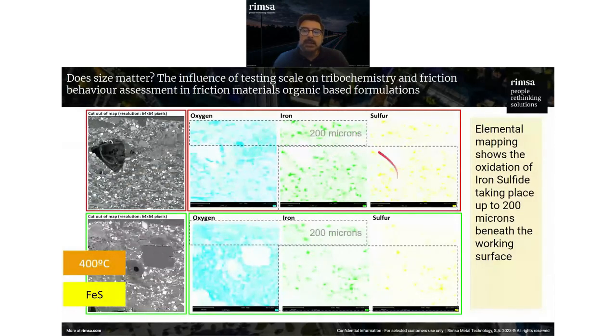We found, the elemental mapping shows that we have the oxidation of iron sulfide taking place up to 200 microns beneath the surface. So we have the same tribochemistry. We have this 200 microns after these 400 tests, where we are getting this iron sulfide that is being oxidized.